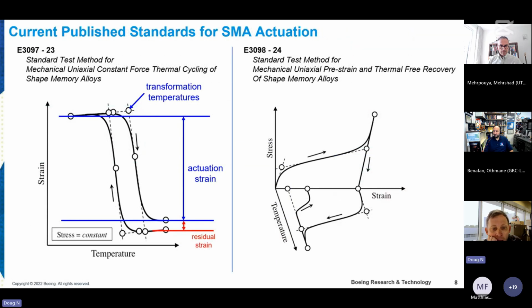So, current published standards. The first one we went after was E3097. This is the standard test method for mechanical uniaxial constant force thermal cycling, and this is one of the most fundamental responses for shape memory alloy actuation. Here we load a specimen, heat it, and then cool it, and then heat it again. So it's the response of the shape memory alloy material under load that gives us the actuation strain, the residual strain, and the transformation temperatures of that material being thermally cycled under load.